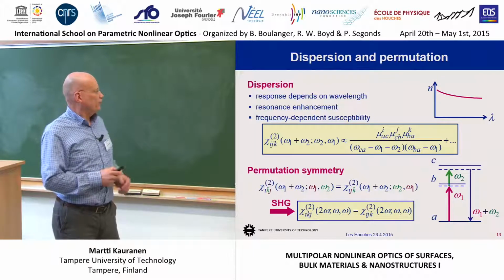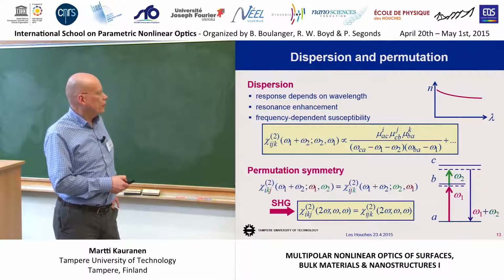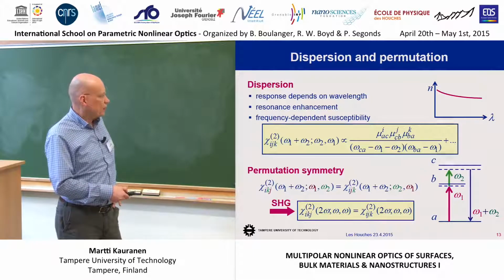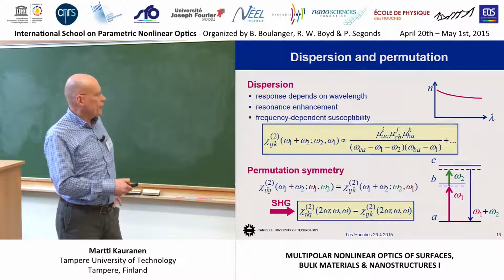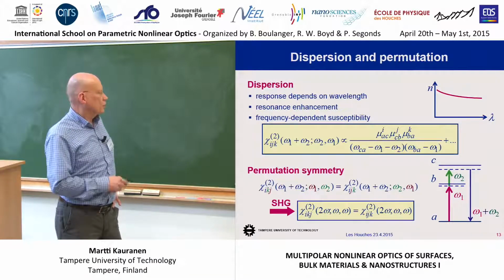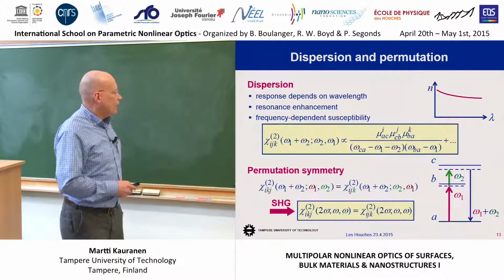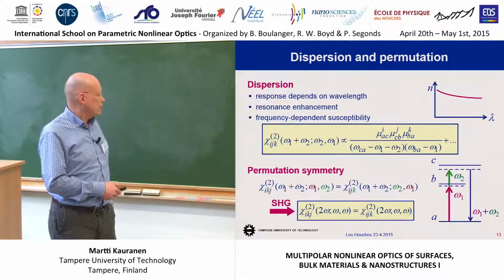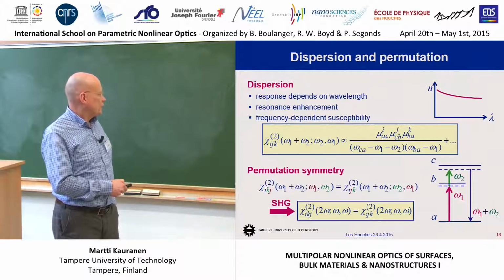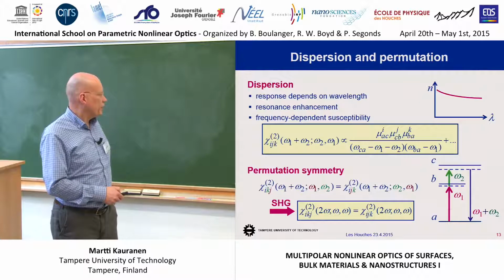And furthermore, if you look at, let's say, a quantum mechanical model of the second-order susceptibility, you find terms like that, where you have these transition dipole moments between different atomic or molecular states, and then you have these resonance denominators. And therefore, for example, if you look at sum-frequency generation where you tune omega 1 close to this transition from A to B, and furthermore, omega 2 close to transition from B to C, then you can get a small number here and also here, sort of a double resonance that can really boost your nonlinear response. And then another detail, if you're looking at some of the conventions, you have so-called permutation symmetry, that in chi2 you can interchange k and j indices at the same time as the respective frequencies. And then, therefore, for second harmonic generation, this tensor must have this kj, jk symmetry. This is just a sort of technical detail.